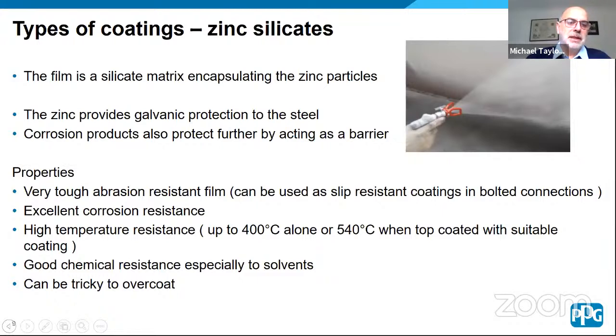Properties of the zinc silicate film. It's a very tough abrasion resistant film. It actually can be used also for slip resistant coatings and bolted connections. There's a couple of standards that are tested there. That's the ASTM A490 and the EN 1090 Part 2. So basically on the slip coating bolted areas, they only apply the zinc silicate. There's no other coating, and then the two zinc silicate faces are put together. So you get your corrosion resistance, but you also get this slip resistance as well. So the bolts shouldn't move when the construction is in place.